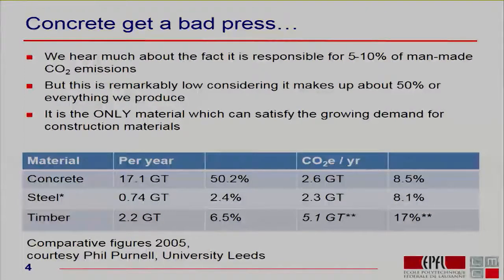You see, concrete makes up about half of what we produce every year, and in doing so, it accounts for about 8% of CO2 emissions. Now, that's actually not a bad ratio. When you look at steel here, there's about 20 times less steel produced than concrete, and it produces almost the same amount of CO2. So the amount of CO2 coming from concrete in terms of performance is extremely good. It's just because we use such a colossal amount of it that overall it produces a lot of CO2.